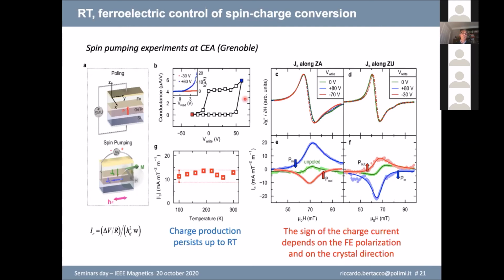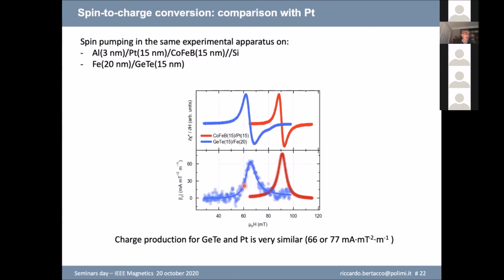And probably the most relevant result is this one. The entity of the charge production is a function of temperature. And you see that from 100 Kelvin to 300 Kelvin, room temperature, it doesn't change. That's a very interesting result, because we are no more working at 2 Kelvin. We are really working at room temperature. Now, what about the size of the effect? Because it's really something that could be used for some interesting applications.